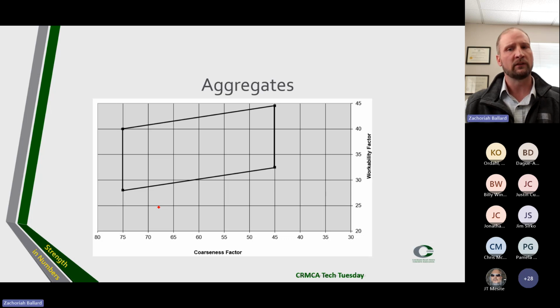From Shilstone's experiences, he determined the workability can be sufficient in certain areas of the chart, and divided the chart into kind of the zones that we have here. We have a zone 1, a zone 2, zone 3, a zone 4, and a zone 5. So we plot our aggregates based on a coarseness factor and a workability factor.